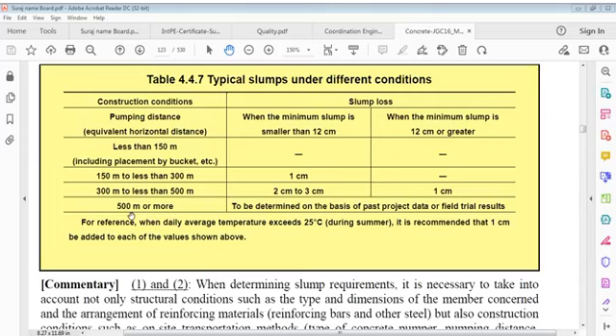Here 12 centimeters is the limit put in by this author, and it says less than 150 meters, including placement by bucket, etc. In this case, slump loss is not mentioned here. For 150 to 300 meters, it is 1 centimeter. For 300 to less than 500 meters, it is 2 to 3 centimeters, and 1 centimeter for placement by bucket. For 500 meters or more, it is to be determined on the basis of past project data. In this case, slump loss is indicated as very small because it is written including placement by bucket.